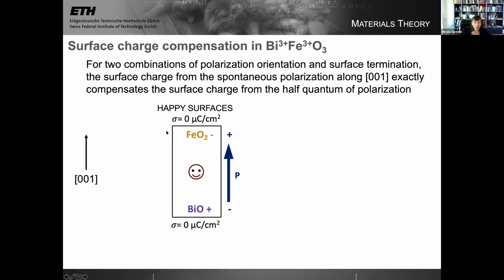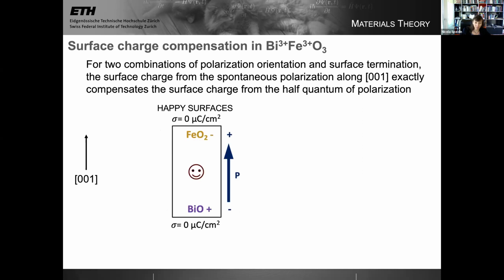So if, for example, I keep the same orientation of the bismuth ferrite, I have the FeO2 minus surface at the top and the BiO plus surface at the bottom, and I polarize it in the up direction. If I just leave the film sitting there, it will do this spontaneously. Then the surface charge from the polarization exactly cancels the surface charge from the layer, and I get a net surface of zero. And so this is where we find happiness in our electronic structure calculations.